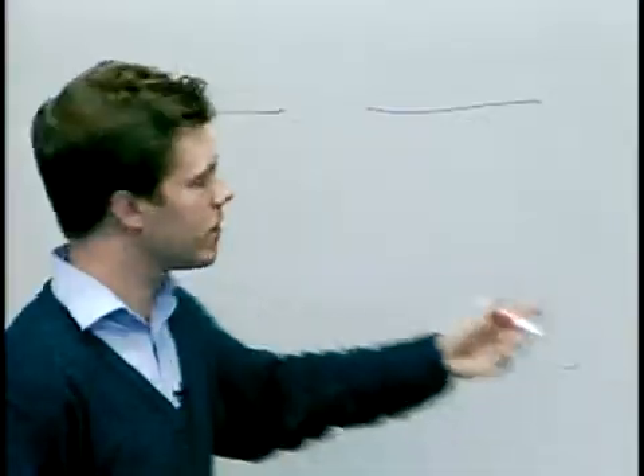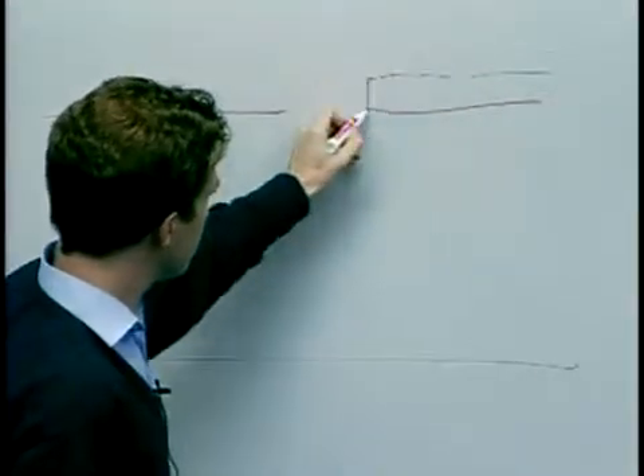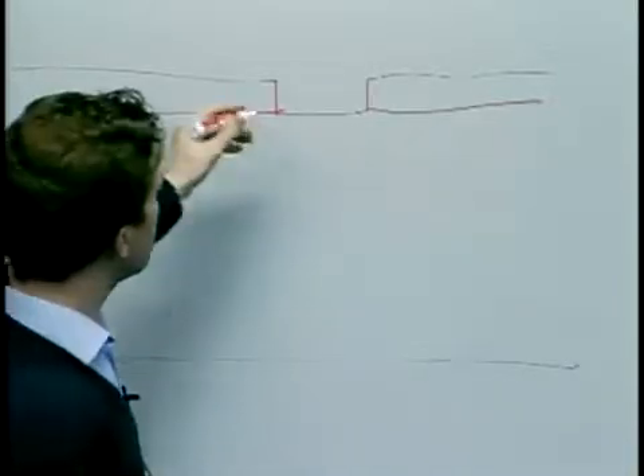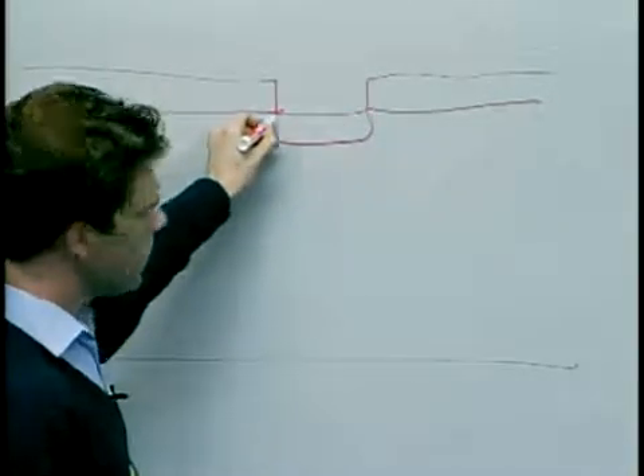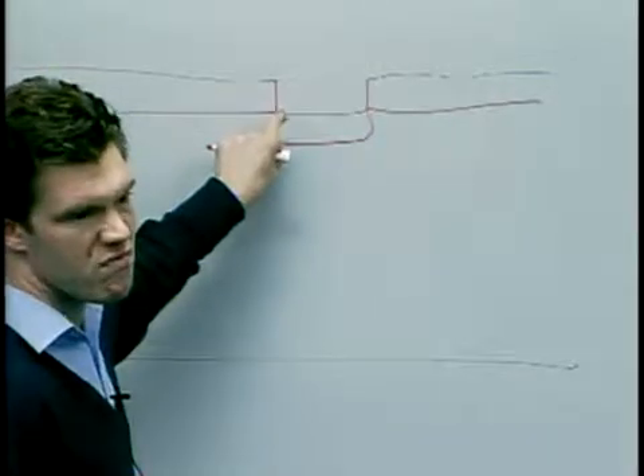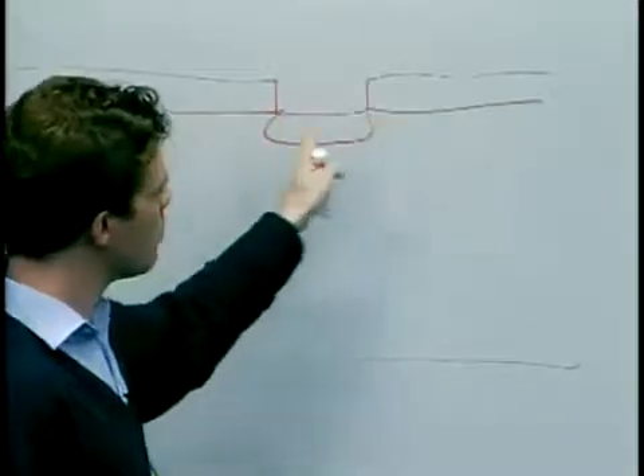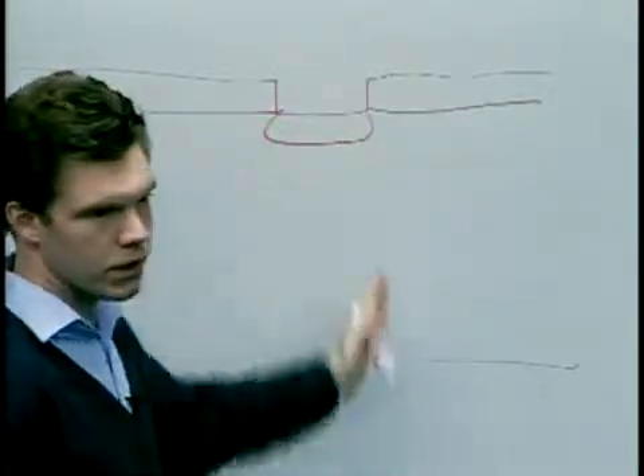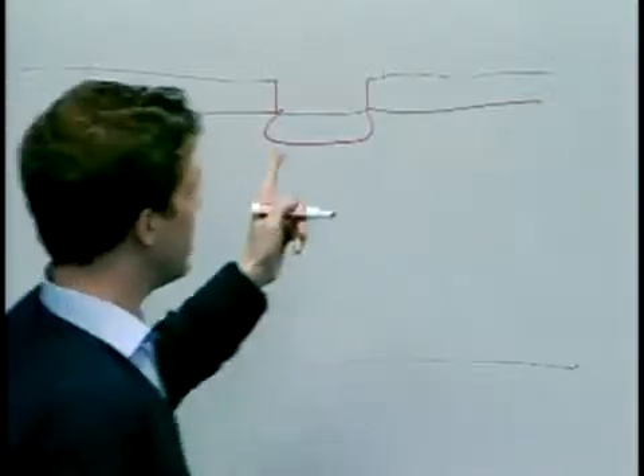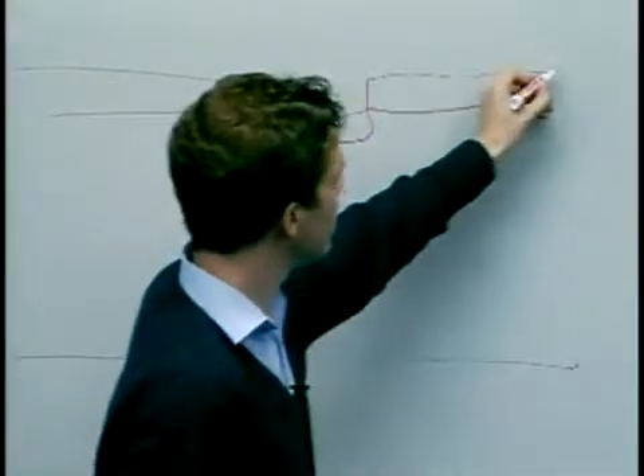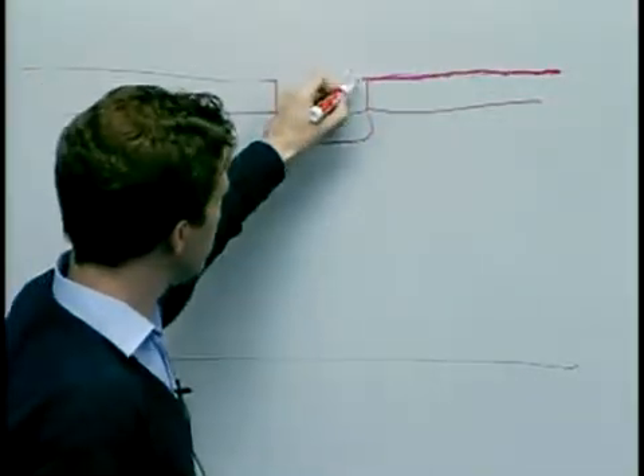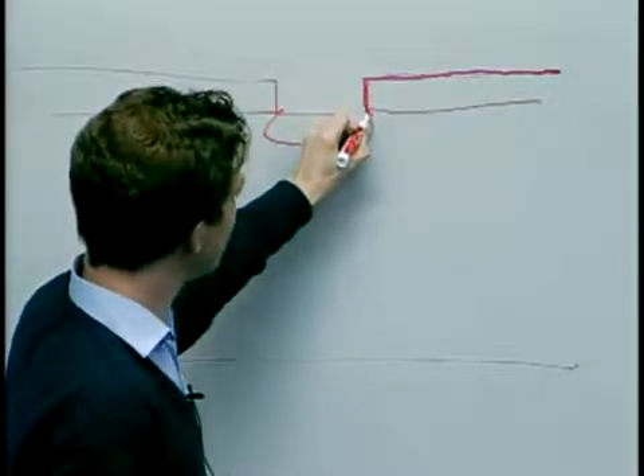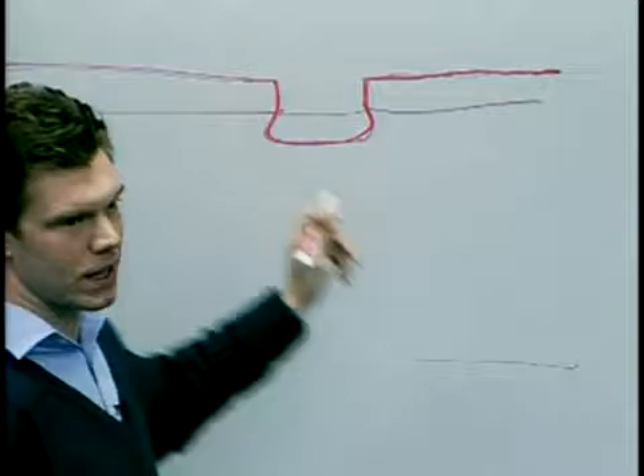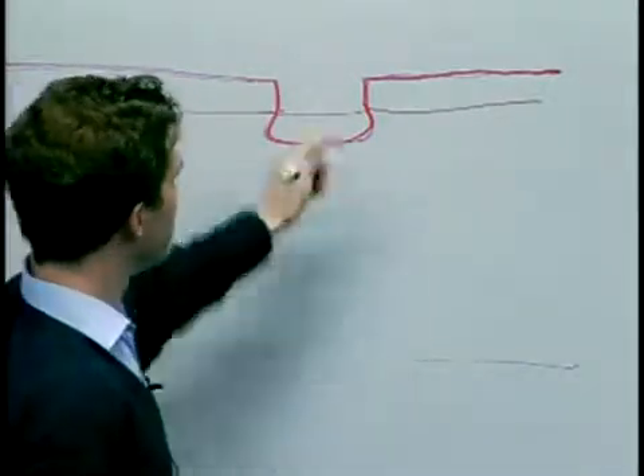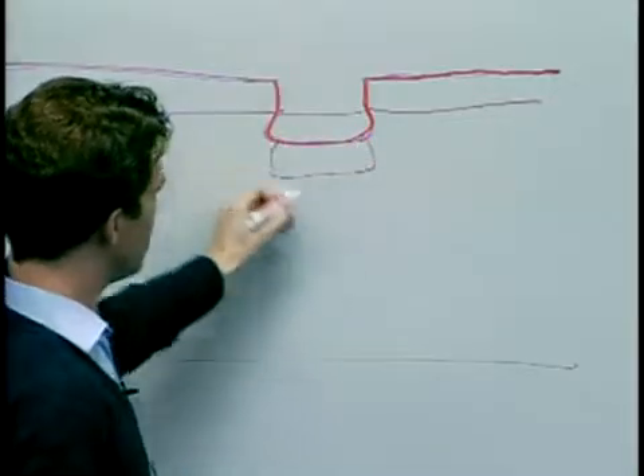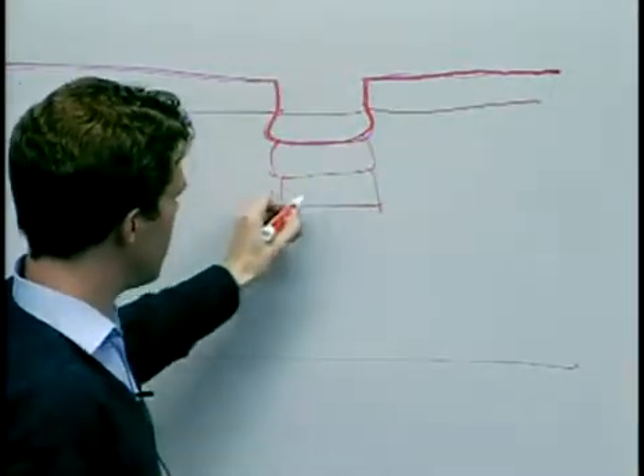series of steps. So, in fact, you would start with the silicon with a photoresist mask or something. You'd do a brief fluorine-based plasma etch that would remove a small amount of material. That's roughly isotropic. So if you want vertical sidewalls, you've got to do something else. And the something else is depositing a polymeric passivation layer. So you change the gas in the chamber to C4F8, which creates what's essentially a Teflon coating that passivates the sidewall of the trench that's developing. Then you go back to the SF6, build up a new notch, and alternate many times.